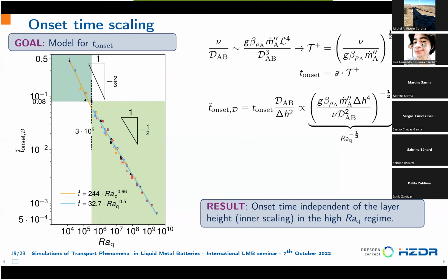If we study the onset of all the simulations, all the configurations of our parametric study, we see that in the light green region, that is at high Rayleigh number, we have a -1/2 exponent, and this is confirmed as well by the inner scaling. At low Rayleigh number, we have the phenomenon that convection starts from the full layer. So we have a different exponent, and we can also see the difference between the high and low Rayleigh number regimes by this line at 0.08. This is the dimensionless onset time, rescaled with the diffusion time scale, and this 0.08 is what we saw a few slides before.